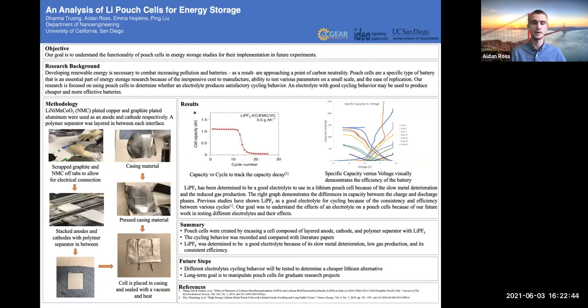So as Dharma said earlier, you need to create a gas bag that will take all these gases upon the first cycle, and then you're going to have to cut them off and vacuum seal the pouch again so that there's more contact between the anode and cathode. And as you can see in the results section on the graph on the right, that is our data that we used. We created this cell and we cycled it around 85 times.